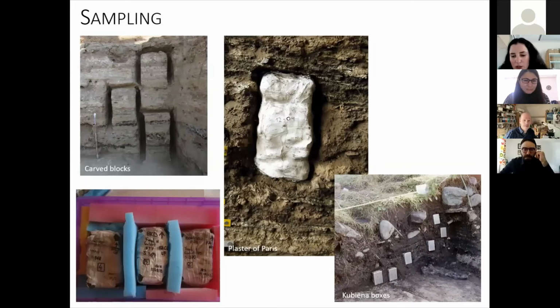Regarding sample collection, I normally carve sediment block in the section, leaving some overlap between blocks if I'm collecting several samples. I extract it and then I wrap it in kitchen roll and secure it tightly with tape. This strategy is particularly adapted to clay sequences, such as the one you have in Neolithic settlements in Anatolia. But it might be tricky to apply to coarser deposits, or deposits that have lots of roots, for example.